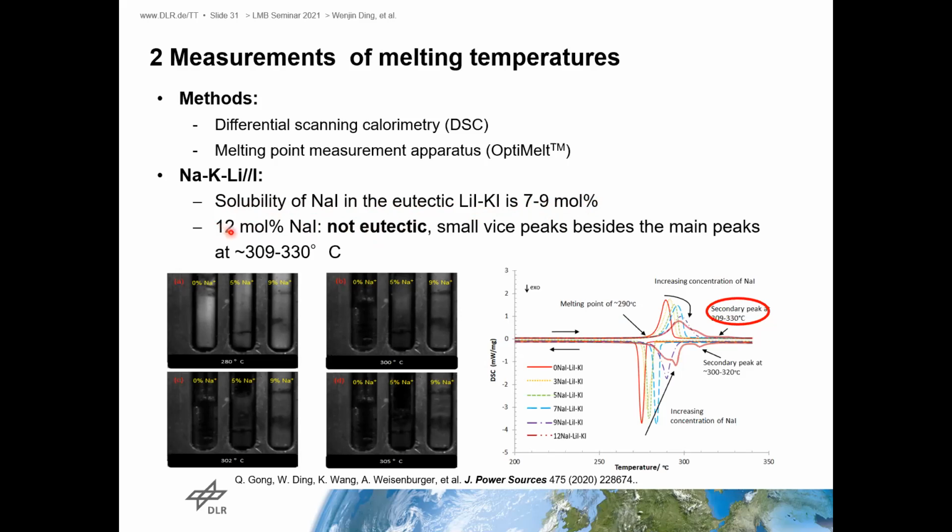If it contains 12 mole percent, in the DSC we can find a second peak, and that means there is some solid salt inside. It cannot be used for the liquid metal battery at this operating temperature range.